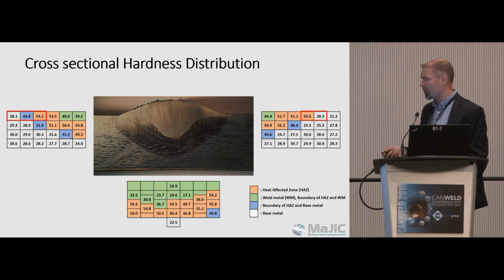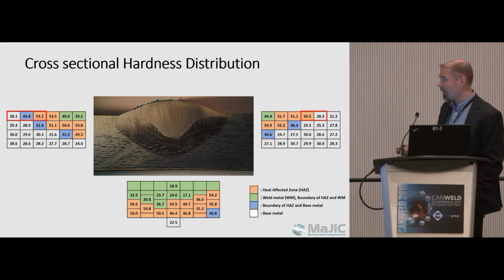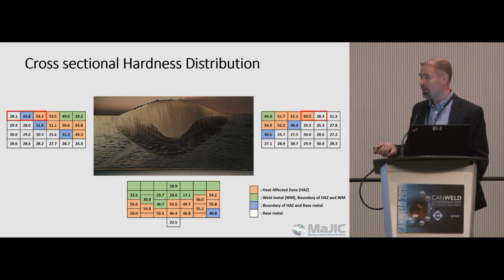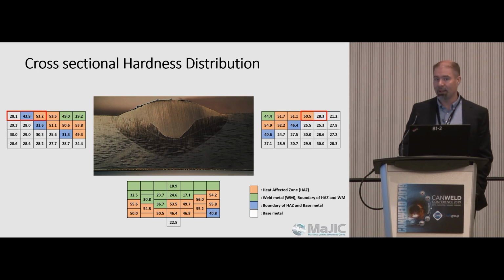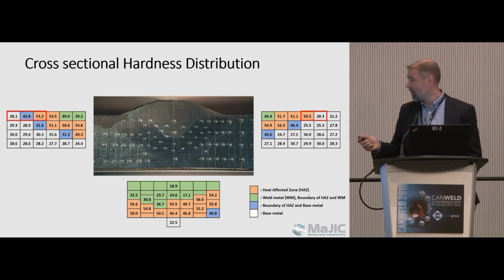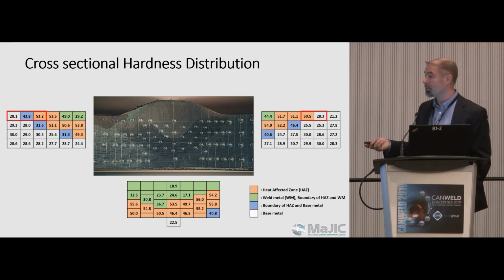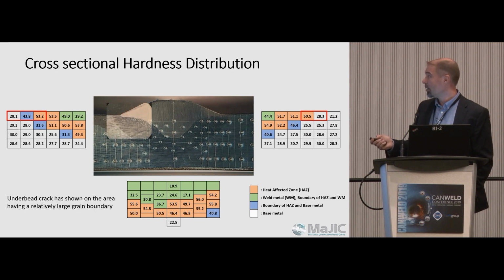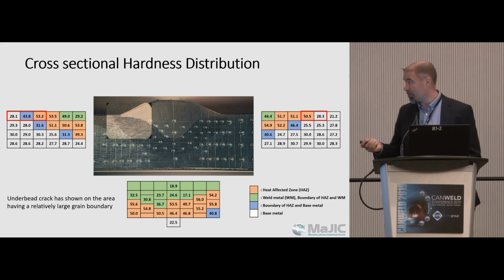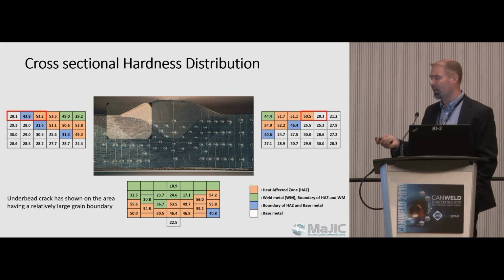Cross-sectional hardness distribution, again, very good correlation. Not quite as good. We see spikes upwards of in the mid 50s, so closer to an 8% deviation from what our predicted hardness was. So we've got some work to do there, and that's the hardness again. You know, the Vickers hardness map is going to be much more telling when we look at that in relation to these cross-sectional hardness distributions.